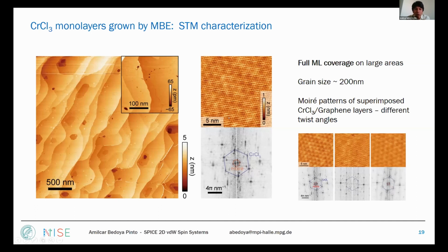But most interestingly, when we go inside one terrace, we can see a very beautiful moire pattern. And this moire pattern is the interference of the chromium chloride and graphene layers. So the existence of moire patterns gives us the hint that the structural properties of the chromium chloride layer on top are very, very nice. And here we can also see that when we go to different parts of the sample, we can see a different moire pattern. And that underlines the fact that we do not always have the same orientation of the domains on a very large scale. So that's consistent with RHEED.